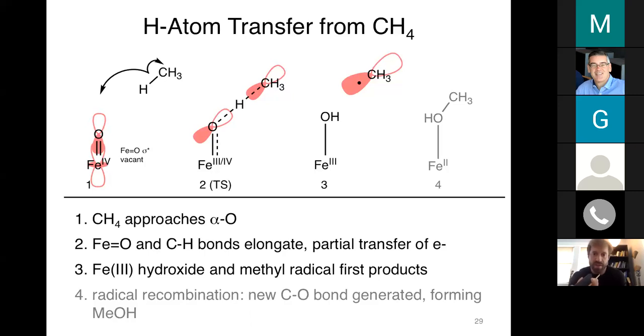And this allows a nice covalent delocalization of the iron-centered hole onto the carbon. So in the transition state, essentially what you have is a nascent methyl radical. And you have the CH bond that's half broken and the OH bond that's half formed. And finally, as you move past the transition state, the hydrogen atom is fully transferred onto the oxygen atom, and the hole localizes on the methyl. So you're left with a methyl radical that's loosely bound to this active site.